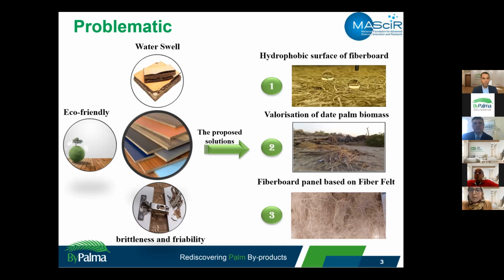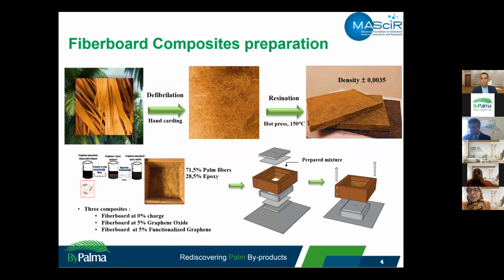So the objective of this work is to remedy this problem via the investigation of hydrophobic surface modification of date palm fiber felt extracted from date palm leaves as a renewable biomass of fiber, and the overall properties of the prepared fiberboard. The palm leaves were hand carded to produce palm fiber felts, and then were used to produce the fiberboard composite by compression molding process with epoxy resin binder at 5 weight fraction % of graphene oxide nanosheet with and without chemical modification. This process was made under a temperature of 150 degrees Celsius for 20 minutes.